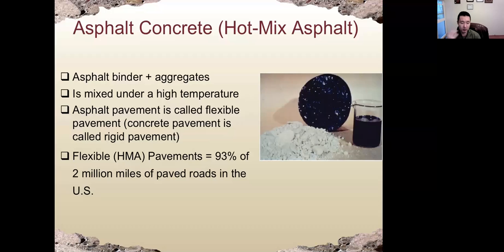Asphalt concrete is mixed under high temperature. The reason for that is, again, at room temperature, asphalt binder is semi-rigid. It cannot be mixed with sand and coarse aggregate. It needs to be heated, or we use cutback or emulsifying agent to liquefy the asphalt binder so it can be mixed with aggregate.